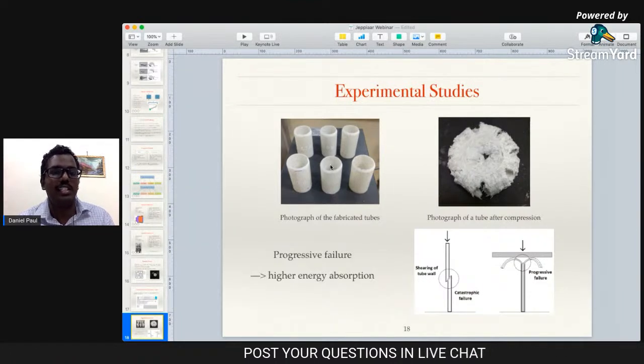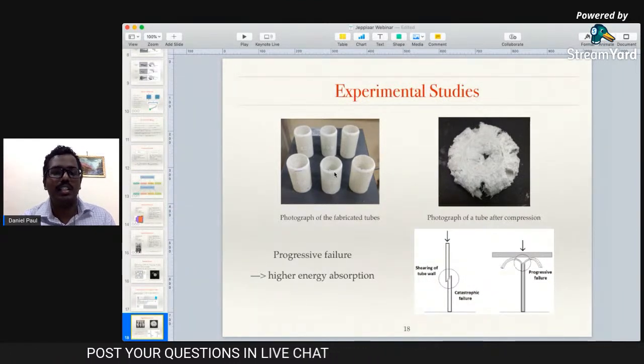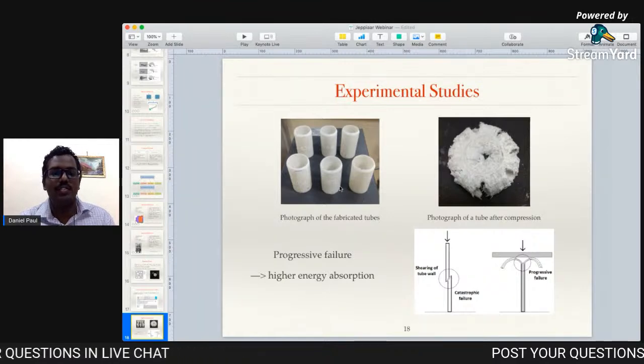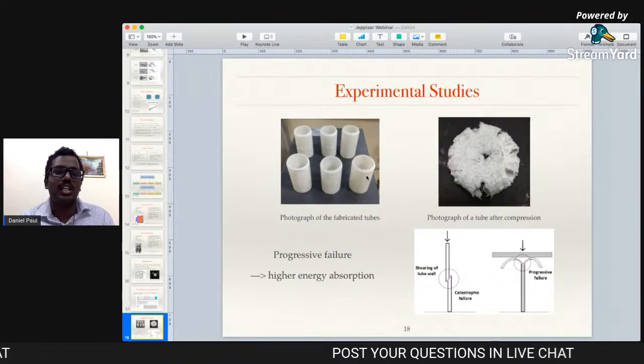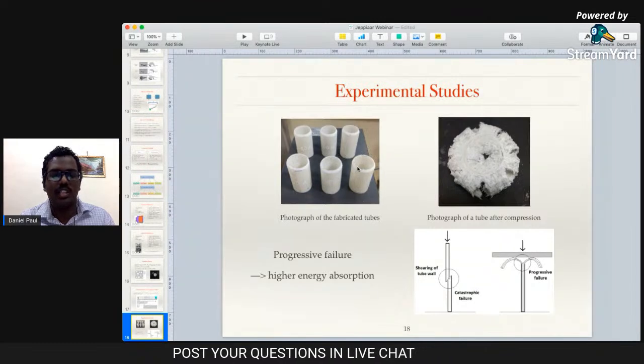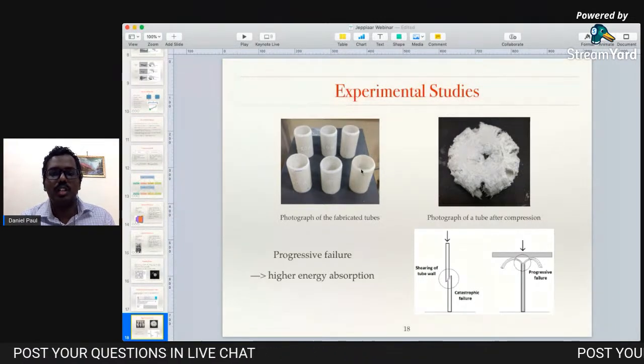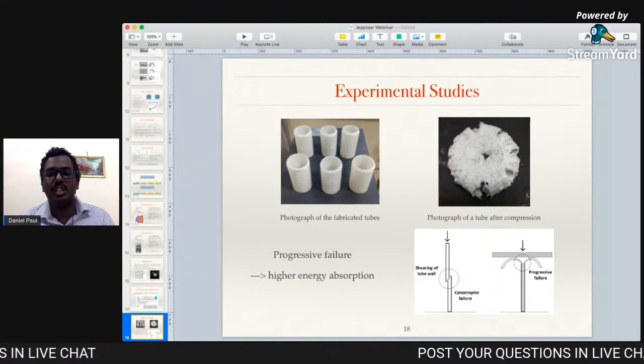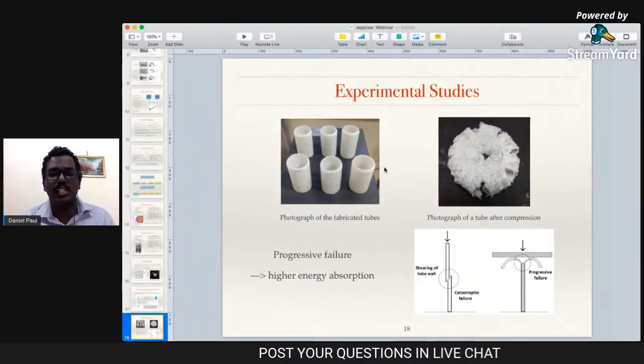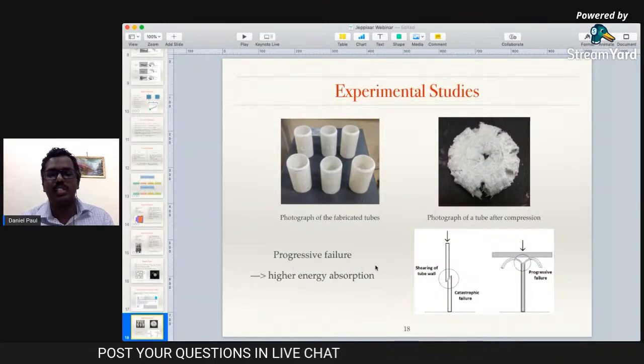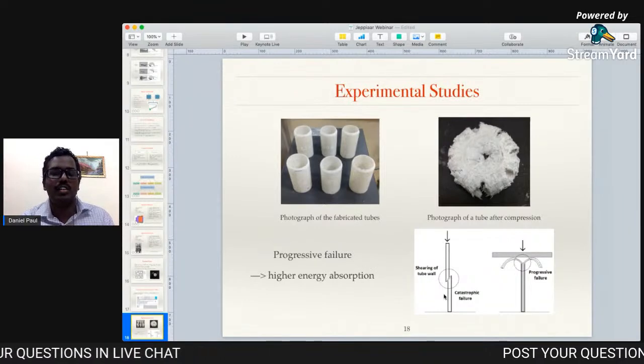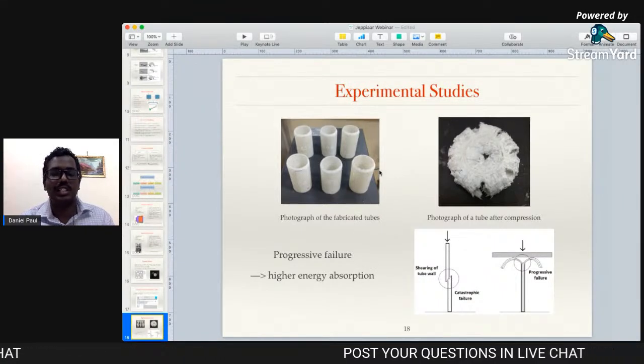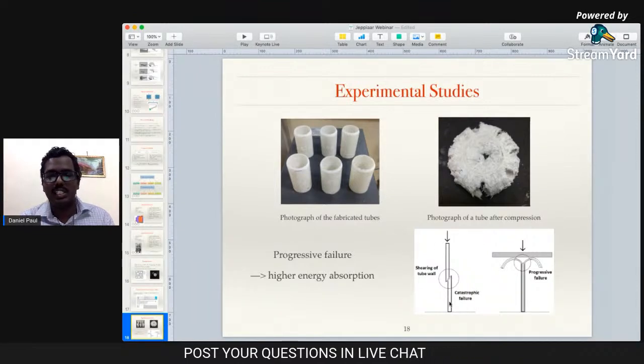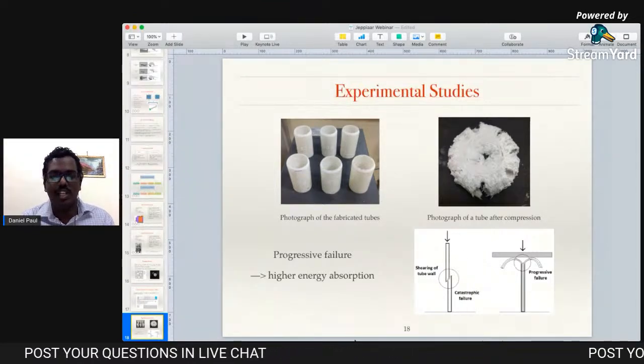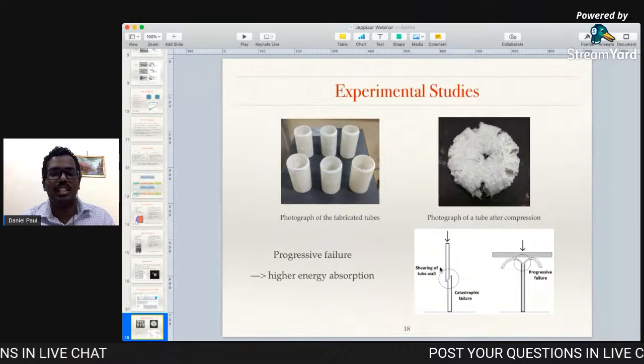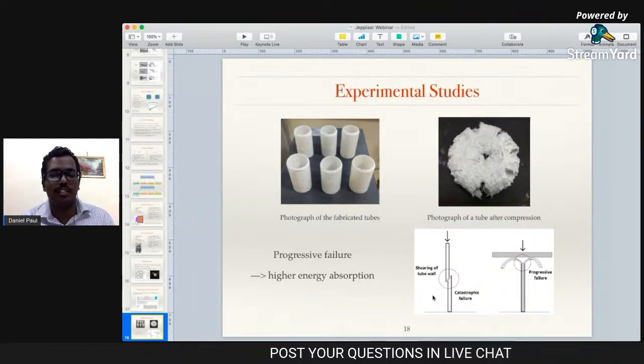They don't get filled inside; they stay hollow, but they're filled within themselves with these glass microballoons, and then we subjected them to crushing loads, to compression. On compression, we found, as is already known, that when tubes compress, they fail in a progressive manner. They don't fail catastrophically. If you take a bar of composite, especially composite, and compress it, it's going to shear off and fail catastrophically. And there's no warning or anything.